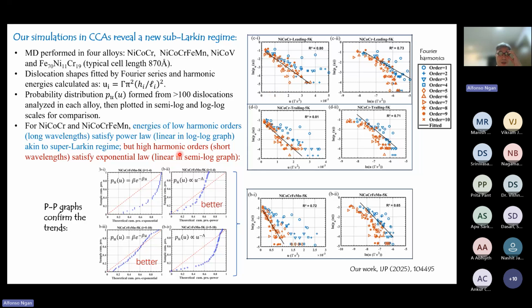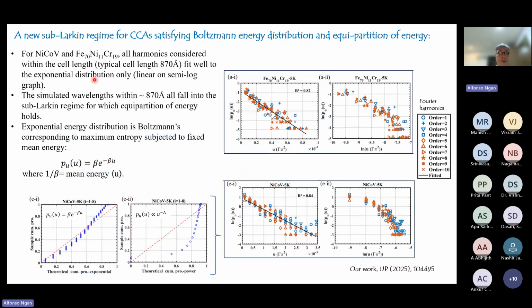So in particular, when we zoom in to high enough resolution, the wavelengths would be short. Then we will be looking at the high harmonic numbers. The distribution of the energy tends to be not fractal, not power law, but exponential. Okay, so that's a very interesting observation, although it does not agree with the previous literature on dilute alloys. So it looks like for these CCAs, we have a new distribution, which is quite different from the situation in dilute alloys.